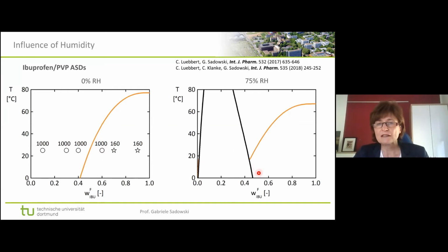And then we predicted what will happen if we go to 75% relative humidity. And what you see is then, in addition to influence on the solubility line, we do get a miscibility gap on the left-hand side. So this is a huge miscibility gap we have here. And here you see this little orange line. This is then the extension of the solubility line on the other side of the liquid-liquid miscibility gap. And then we were curious to know whether this is right or wrong.